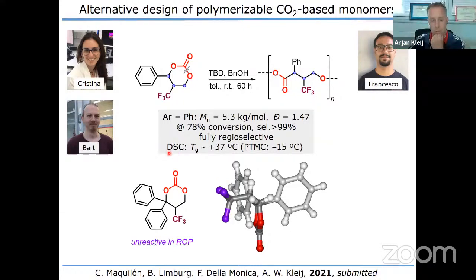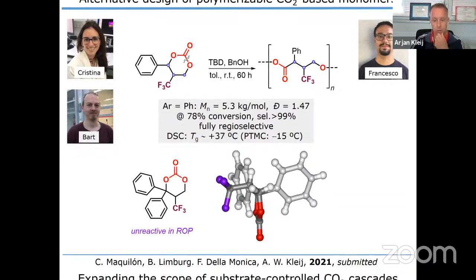And if we do differential scanning calorimetry, we see that the glass transition temperature of that polymer, or maybe I should say oligomer, is plus 37. And if we compare that with the literature data for the polymer that has no substituents, then we see that there is almost, up to more than 50 degrees of difference in the glass transition temperature. So that actually nicely shows that indeed substitution of the polymer makes sense if you want to create polycarbonates with different properties. However, if you increase the steric bulk too much, so this is a tri-substituted cyclic carbonate, we saw that this is unreactive in ring opening polymerization, and that makes perfect sense because in the X-ray we see that this carbon center is actually blocked from both sides for an incoming nucleophile. And so that gives also important information in how to design future monomers.